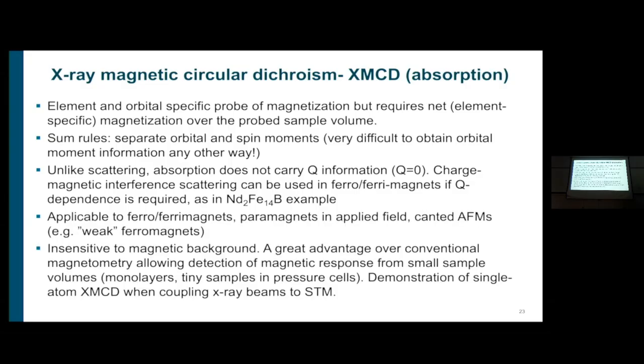technique. You can use it in ferro- and ferrimagnets. In ferrimagnets, you have two sublattices with different magnetization. So again, it's element specific. If you have a paramagnet and you apply a magnetic field, you orient the moments and you induce magnetization, you can use it. If you have an antiferromagnet that is canted, either in magnetic field or naturally, like in a weak ferromagnet due to, say, the Dzyaloshinskii-Moriya interactions, then you can also use it. And the most important thing is that it's insensitive to magnetic background. So that's a great advantage over conventional magnetometry, because if you have very small magnetic response in a huge background from, say, a monolayer sample on a thick substrate or a tiny sample in a pressure cell that has a magnetic response, it's even demonstrated that you can measure a single atom response by coupling X-rays with a scanning tunneling microscope.